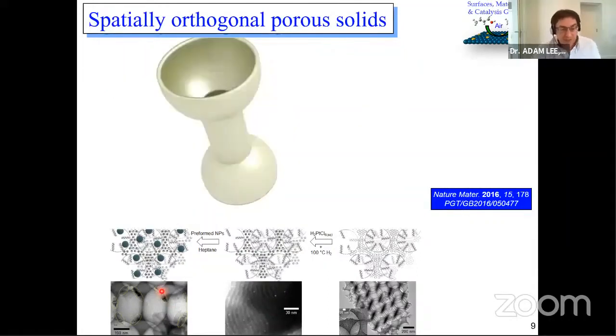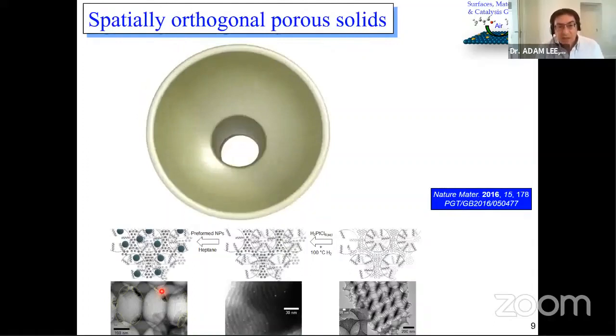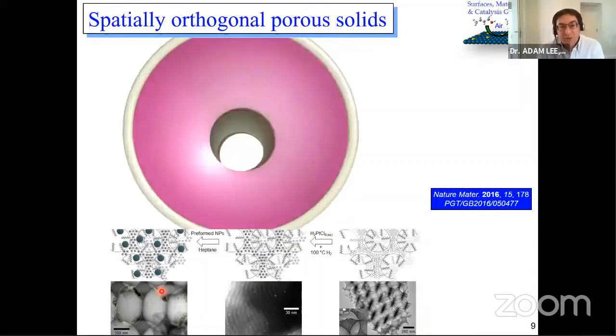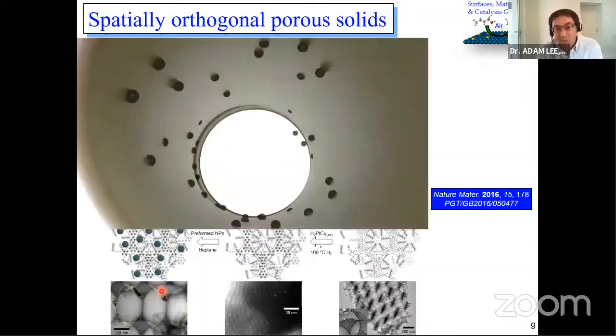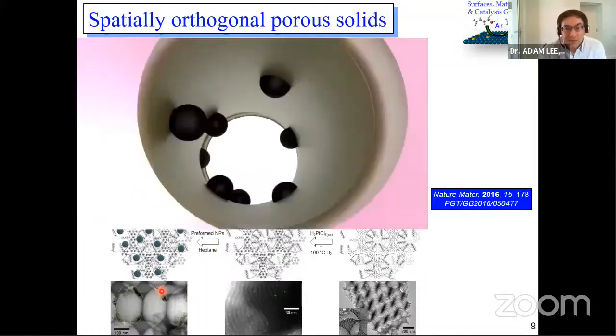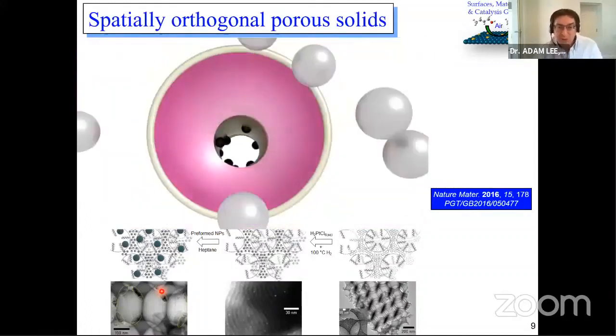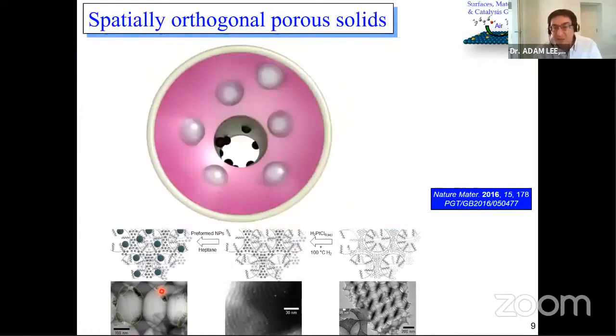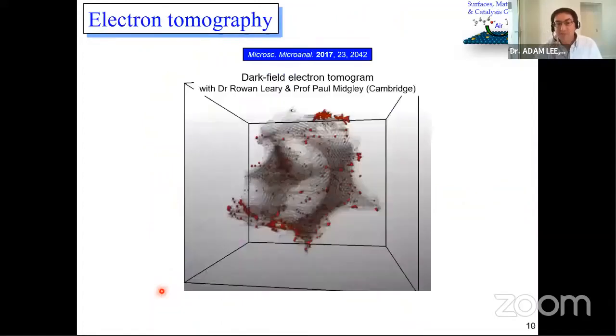I'll just show you a little animation, makes it easier to understand. So we take our porous architecture, we turn it pink, we hydrophobize the large pores, we put platinum nanoparticles into the small pores, then finally we put larger palladium nanoparticles selectively into the bigger pores. So we've got two types of catalyst site in the same particles, but in separate parts of the pore network.